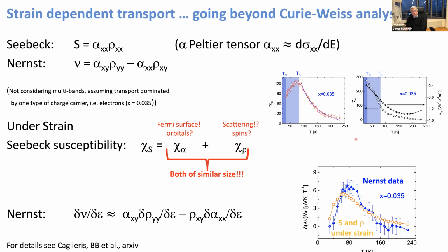This is a susceptibility from the resistivity, which we know, which I have shown you earlier. And you can do this analysis, and then you find out that you definitely need two kinds of susceptibilities. You cannot take the resistivity values to explain the Seebeck effect. That's also already clear from the concentration dependence, and both have similar size. So there's certainly a very strong change of the Fermi surface. It's quite natural to assume that this is due to some orbital degrees of freedom, and that might be a starting point for more calculations.